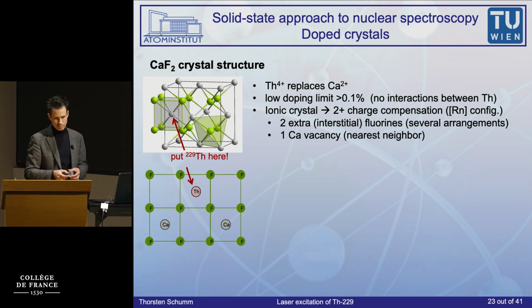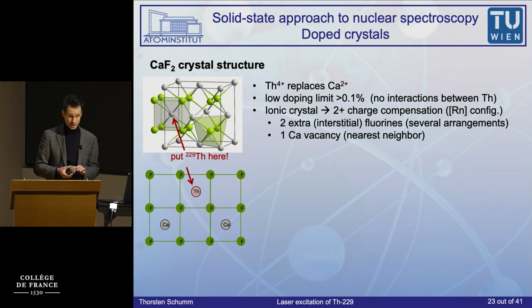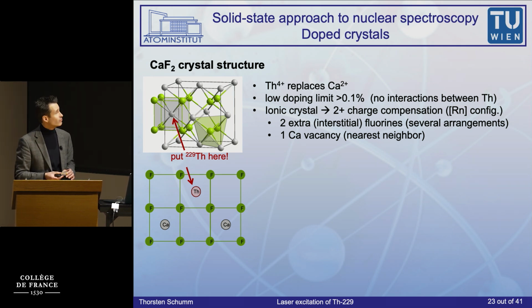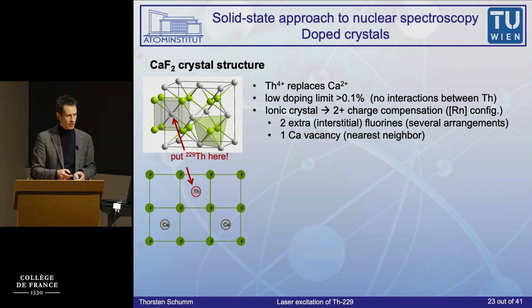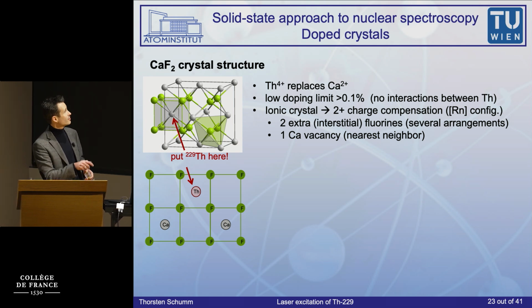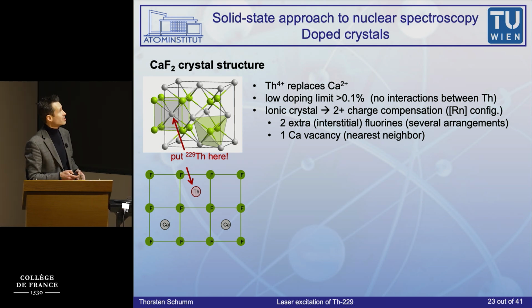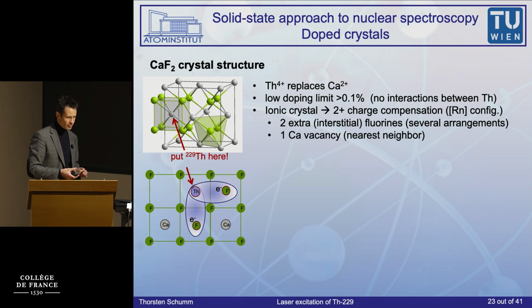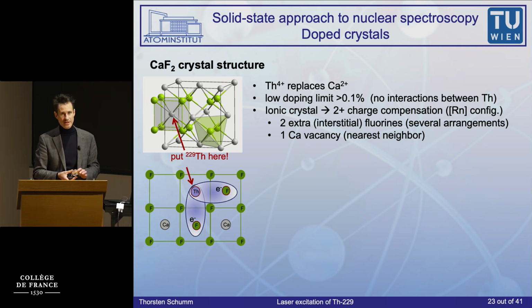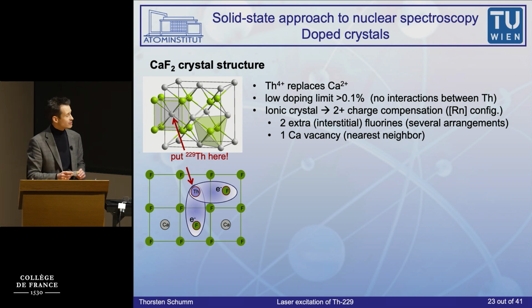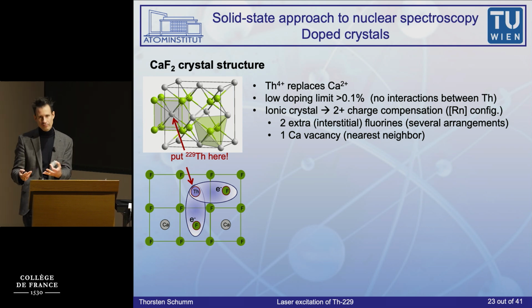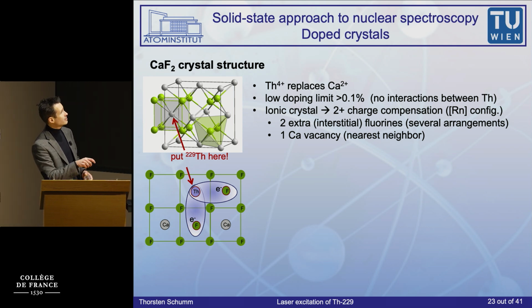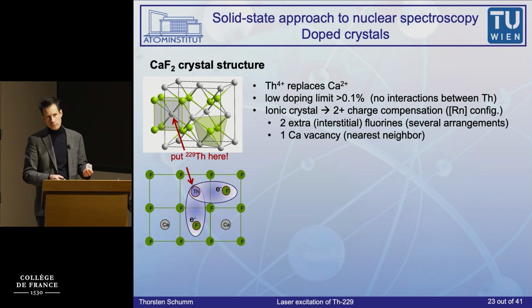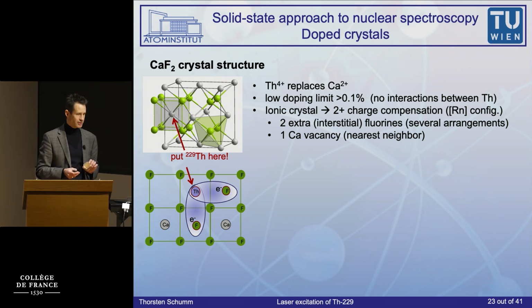However, thorium 4+, as I already said, wants to be 4+. It wants to get rid of its outermost 4 valence electrons. Calcium wants to give away 2. So this one actually has 2 extra electrons that we have to take care of. And there's a charge compensation mechanism that takes place in this crystal that puts in 2 additional fluoride ions to eat up these 2 electrons. You can imagine this as defect physics in solid states. This is the microscopic configuration we, to some extent, believe is taking place in that crystal.